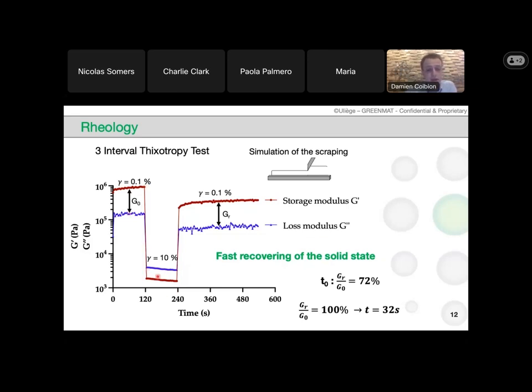Then in the second part of the graph, we are applying a shearing state, corresponding to the scraping. At this stage, we can see that the liquid modulus is above the storage modulus, the solid modulus. So here we have a good spreading of the paste on the plate. And when we stop the shearing, we can see a really fast recovering of the solid state compared to the loss modulus. So as we compare the ratio between the solid modulus and the liquid modulus before the scraping and after the scraping, we can see that we have an immediate recovering of 72% of the initial ratio, and we have to wait only 32 seconds to have the full recovering.